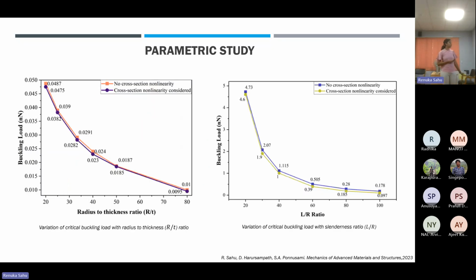We also did a parametric study to see how the buckling load varies with the radius-to-thickness ratio and the length-to-radius ratio. Keeping the thickness constant and varying the radius, we obtained this variation for two cases: one where cross-sectional non-linearity is considered, and one where it is not. For pure axial compressive buckling, the variation is not much, but at higher radius-to-thickness ratios, there is a larger difference between the buckling loads for the two cases.